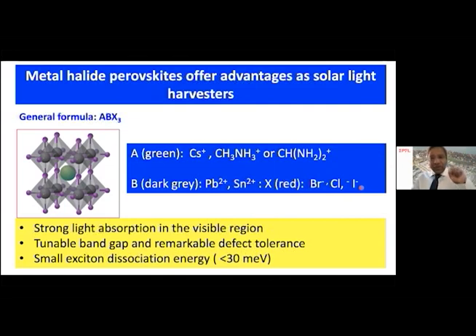At the same time, you can also make a minor band gap tuning by going from cesium to methyl ammonium to formamidinium. At the same time, by changing the B cation, you can also decrease the band gap significantly, going from lead to tin 2 plus.